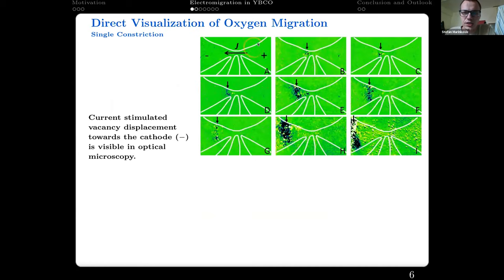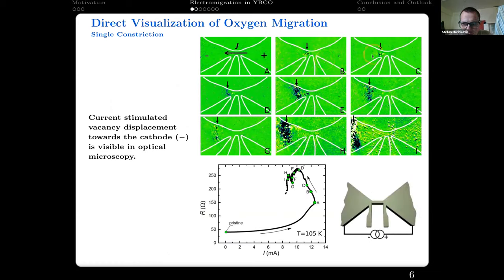The outline here on this image shows the bow tie-like structure, and the electromigration process starts at A and proceeds through to E. As you can see, these are differential images. That means we subtract sequential images one from the next. And as you can see, there is a propagating front of change in the reflectivity of the material that we can see as electromigration progresses.